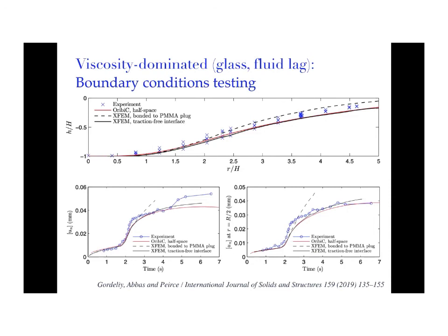So I would say, yes, there is certainly dependency of the solution for the crack width and fluid pressure on the crack path. Now here in this test, it's not only the crack path, it's also the different boundary conditions. But if you use the same boundary conditions and have slightly different crack paths, it will still affect the pressure and the crack width, but not that much.